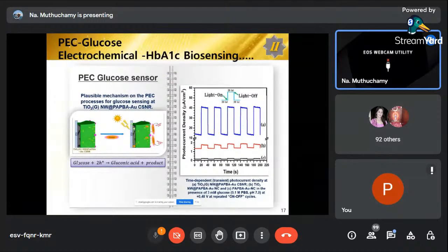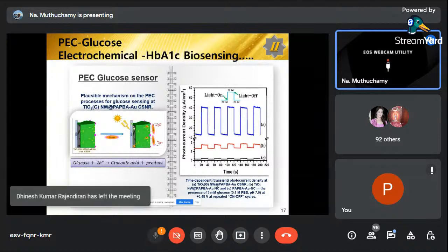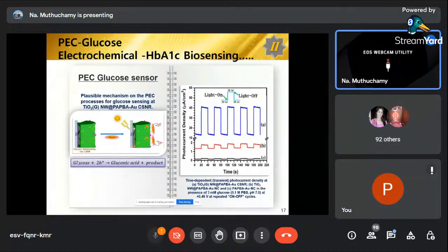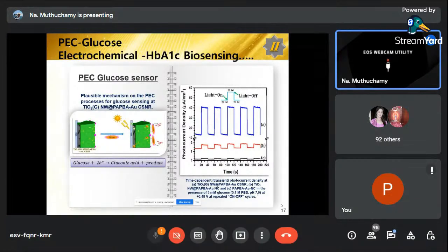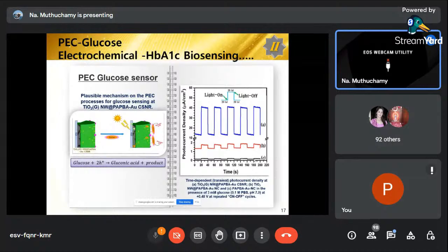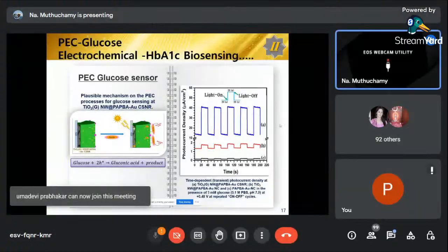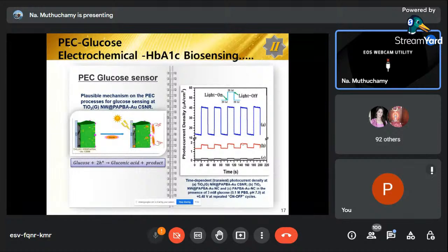It can enhance the conductivity of the current. Also, it can bind the glucose molecules from the analyte. So the boronic OH group is really helpful for the bifunctional role in this work. You can see that we prepared three kinds of material: one without polymer, another without graphene, and another with only gold nanocomposite without TiO2. Without TiO2 in C, there is little photo response. When you include TiO2 nanowire without graphene, there is also some enhanced current due to the semiconducting property of the TiO2. When we include the graphene, the photocurrent increases.